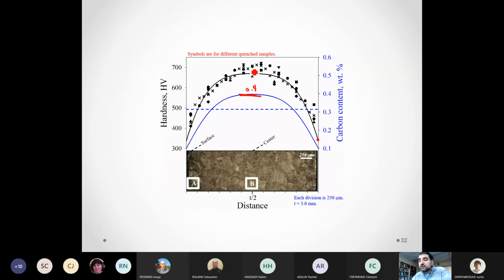The hardness at the center is as expected, around the 700 Vickers. At the surface, it's much softer, around 400 Vickers. And you could see here, there is no sharp interface along the microstructure. The microstructure gradually changes from low carbon martensite and sometimes bainite at the surface to a higher and higher carbon martensite towards the center.